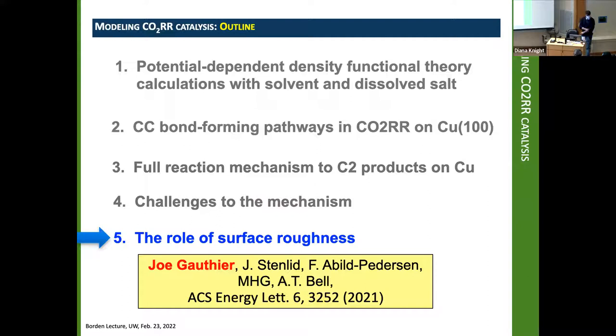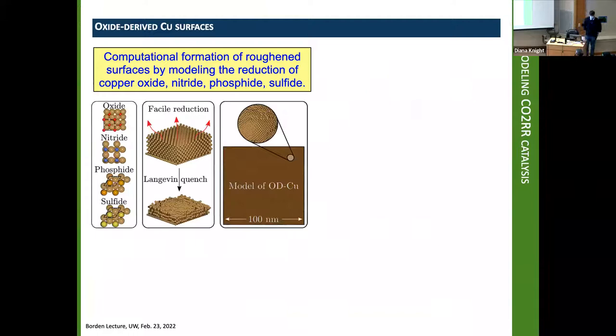Then one last story, and I'll then wrap up and try to leave time for questions, is the role of how you process copper, which is under active study at the moment. And we began looking at the role of surface roughness. This is the first computational work to carefully study the effect of surface morphology on CO2 reduction reaction activity. What we did computationally was to make copper oxide, nitride, phosphide, and sulfide, and deoxygenate, denitrogenate, dephosphorize, and desulfurize these materials to leave behind oxide-derived, nitride-derived, phosphide-derived, and sulfide-derived copper.